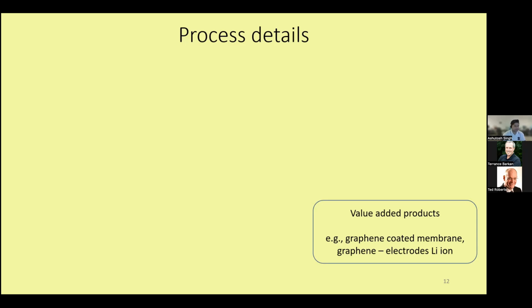More than a 50% increase in the power density of the redox flow battery. We think it's because the layer is so thin that it's very selective to just H plus ions, and it's reducing the crossover. It's also doing a bit of electrochemistry in there because of the presence of heteroatoms. And we could see that it was adding value to those sectors as well.